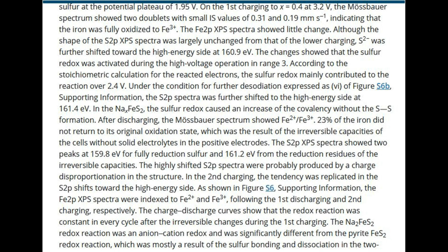In the second charging, the tendency was replicated in the S2p shifts toward the high energy side. As shown in figure S6, supporting information, the Fe2p XPS spectra were indexed to Fe2+ and Fe3+, following the first discharging and second charging, respectively. The charge-discharge curves show that the redox reaction was constant in every cycle after the irreversible changes during the first charging. The Na2FeS2 redox reaction was an anion-cation redox and was significantly different from the pyrite FeS2 redox reaction, which was mostly a result of the sulfur bonding and dissociation in the two-electron reaction.